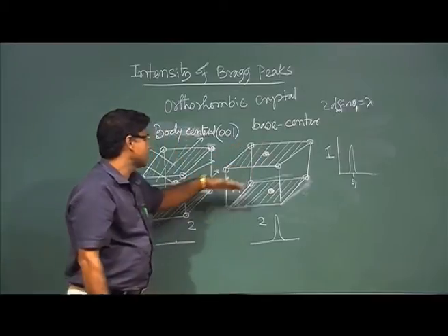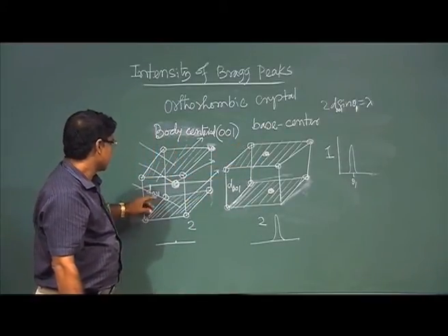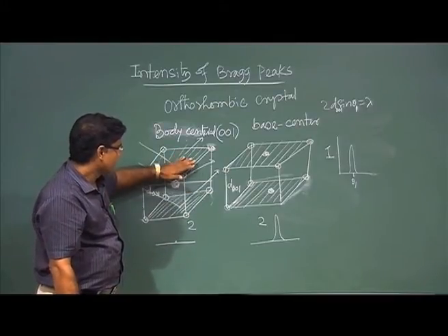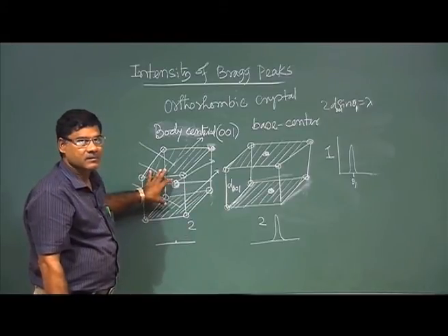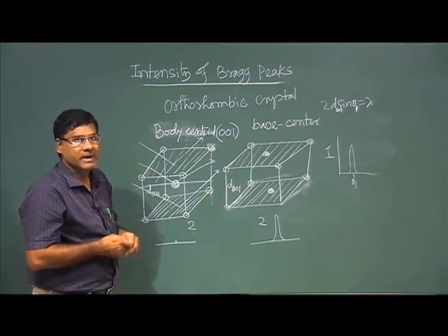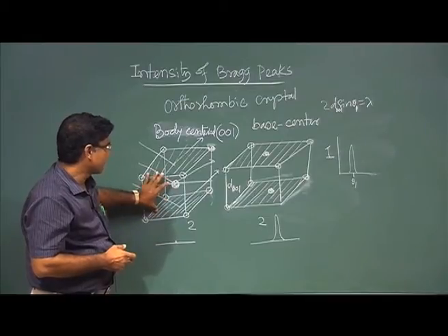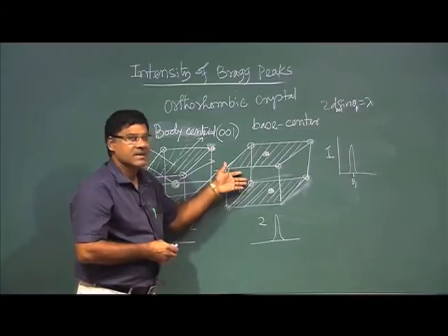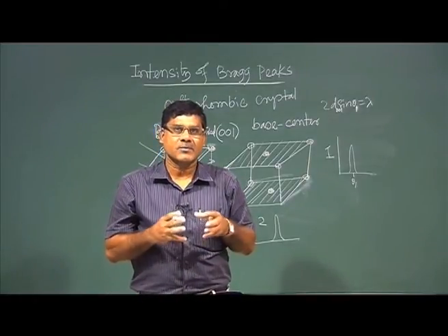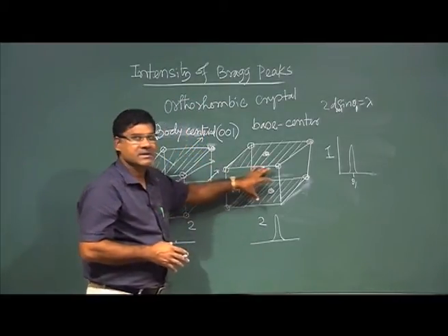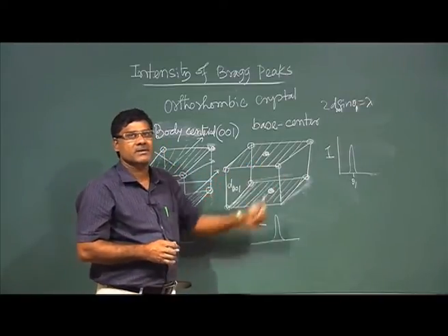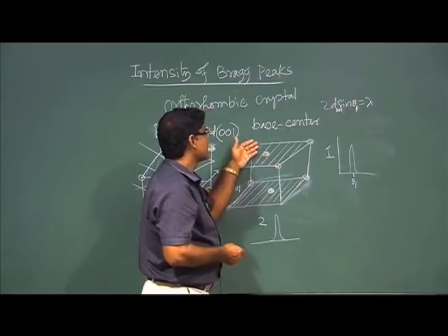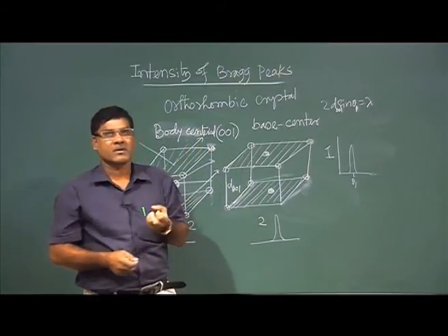So, intensity does not depend, of course, on this lattice spacing. It depends on the plane, because different planes have different areal density. So, that is fine, but for the same plane, intensity also varies because of the distribution of lattice points or atoms in its cell. So, here and here the difference is the distribution of lattice points in the cell. In terms of basis, I was talking about whether atoms are exactly sitting on the lattice point or a group of atoms is sitting around it.